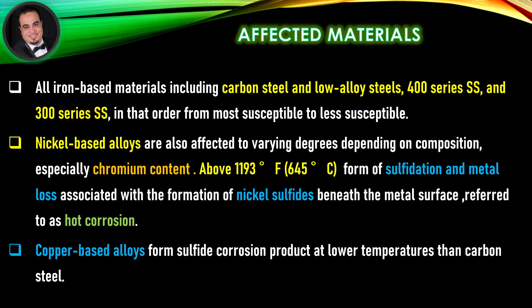Nickel-based alloys are affected depending on composition, especially chromium content. Above 1193°F, a form of sulfidation and metal loss is associated with the formation of nickel sulfides beneath the metal surface, referred to as hot corrosion. Copper-based alloys form sulfide corrosion products at lower temperatures than carbon steel.